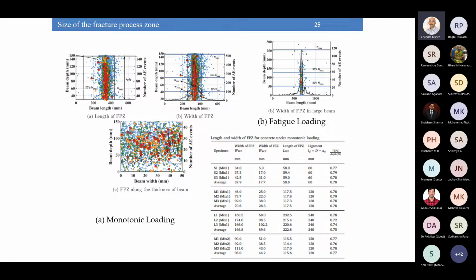You can see a black line here. So the intersection of this histogram with about 20% of the total acoustic emission events will give us the depth of the fracture process zone. So same thing here, we have the histogram here, and about 20% intersection of this line. Basically this 20% line was arrived at by other researchers, which is available in the literature, and they had proposed this 20% line through which we can determine the width of the fracture process zone.